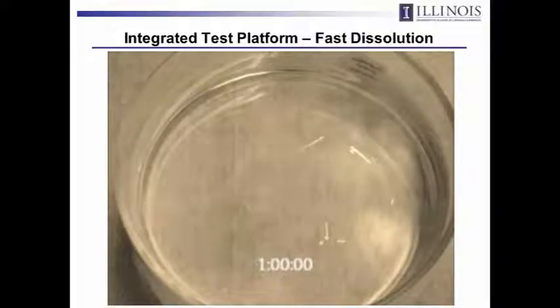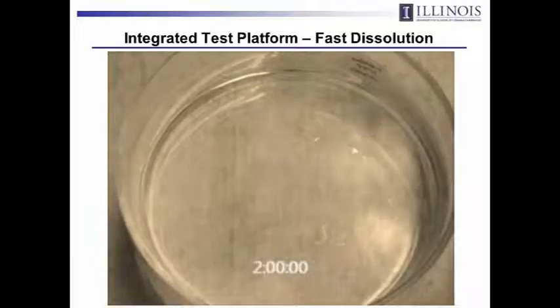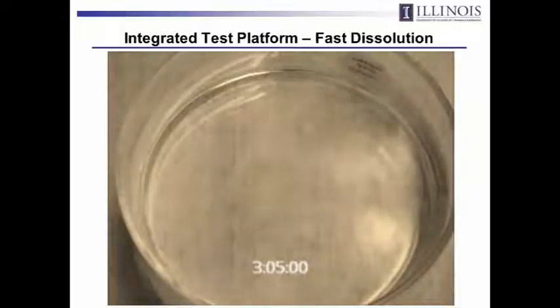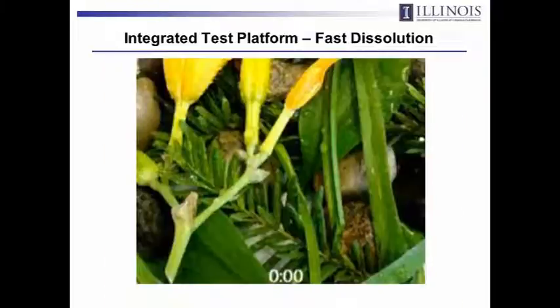After disintegration, then you begin to see the magnesium traces themselves undergo hydrolysis to magnesium hydroxide. So over the course of a few hours, the magnesium will completely disappear. The silicon takes a lot longer, but the silicon is so thin, so small, you don't really see it here. But it, as well, given enough time, will disappear. So that's what it looks like. So you can imagine what it would look like in the field. This is just an example.